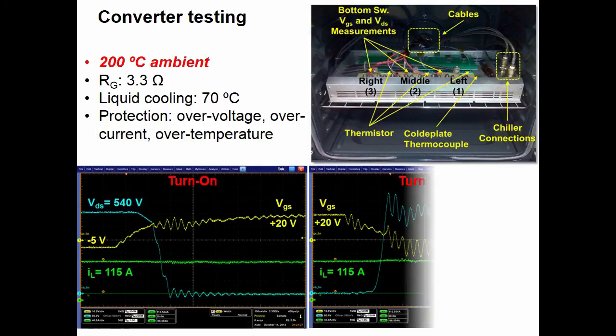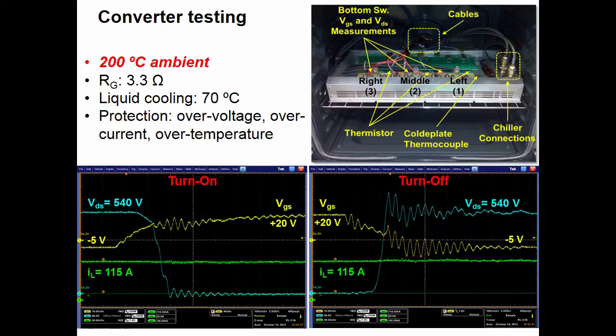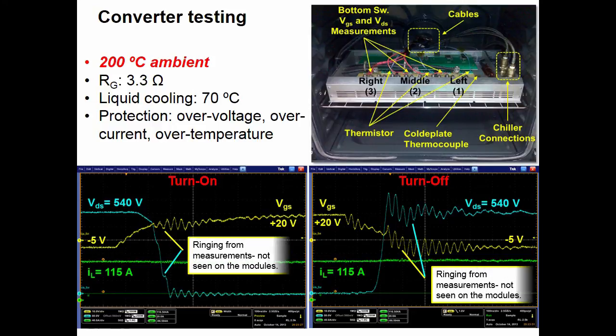The turn-on and turn-off waveforms from the double pulse tests are shown here, where the yellow waveform is the gate source voltage, the blue waveform is the drain source voltage, and the green is the inductor current. The ringing shown in these waveforms is from the measurements and is not actually seen on the modules. Due to the lack of high-temperature voltage probes, long high-temperature wire was extended from the power modules to outside the thermal chamber. Testing at room temperature verified that this ringing is due to the added parasitics and noise from the long twisted wires and is not seen on the modules.